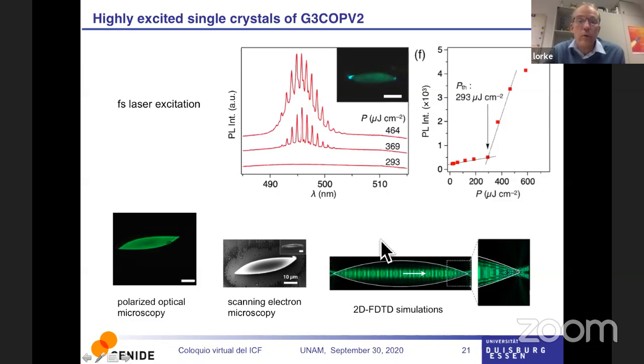Here's a scanning electron microscope image, and here you see the photoluminescence, this time under very, very high excitation. That's what I told you in the beginning is something that you need to build a laser. And since you can't continuously excite these fragile molecules, they used a very short, very high power laser excitation, femtosecond laser excitation. And depending on the entire deposited energy in microjoule per centimeter squared, they either just saw a very weak signal, or they saw these very characteristic peaks that are these resonances inside the parallel plate resonator. And that's already a good sign if you want to build a laser.